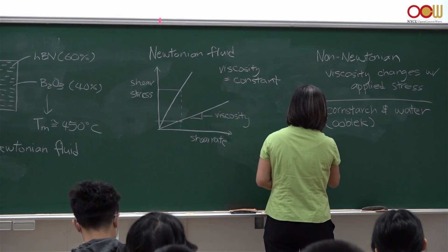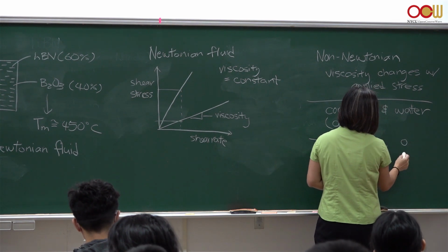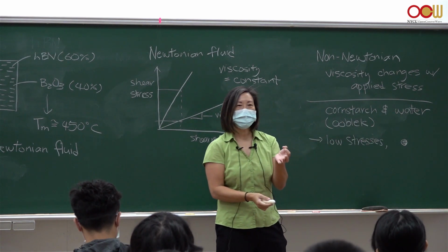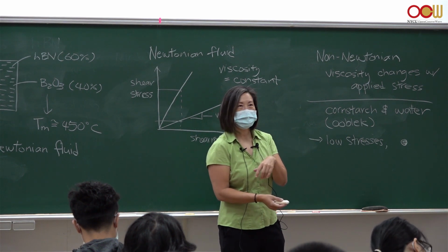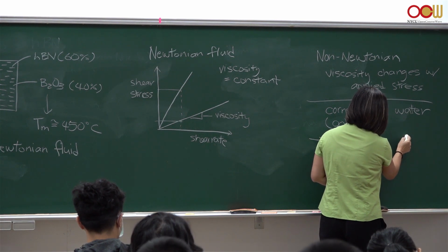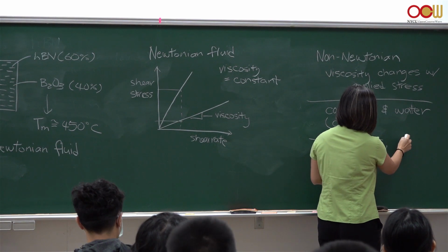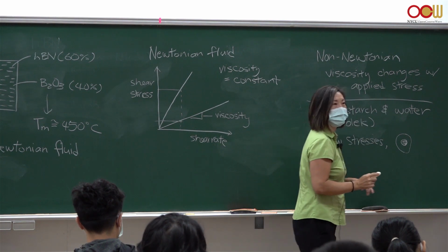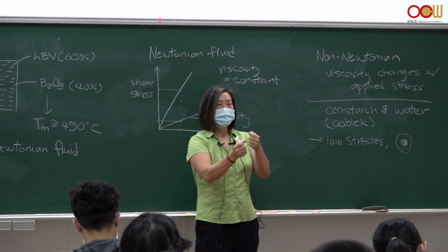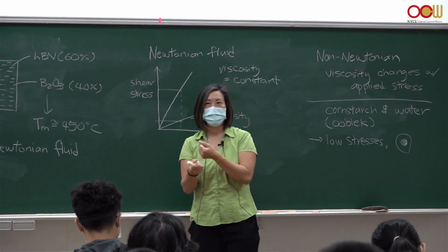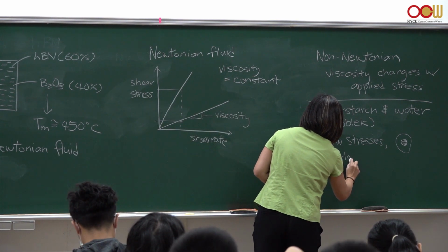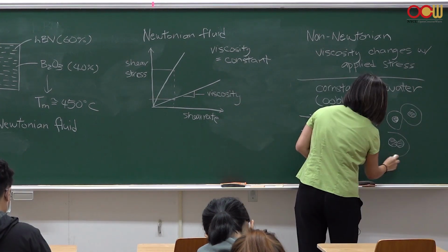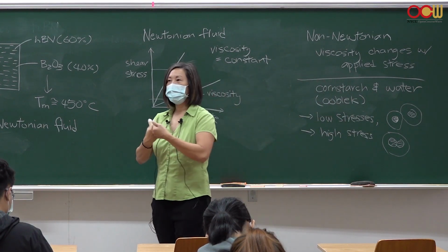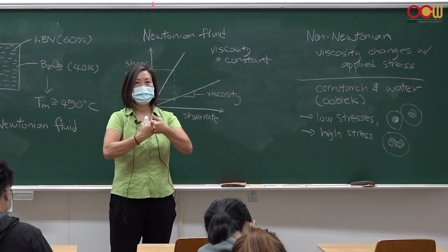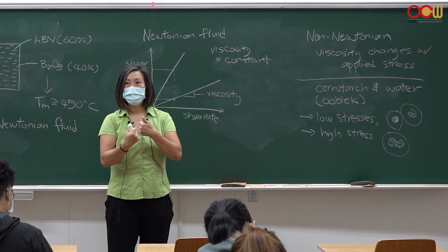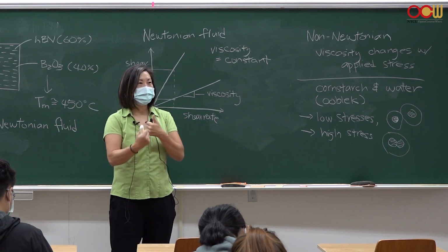So cornstarch and water at low stresses. The cornstarch particles, this is cornstarch, they're very small. They're on the order of 1 micron, 0.001 millimeters. At low stresses, each of the cornstarch particles is surrounded by water. The water coats each of the particles, so the particles slide past each other very easily. But when you apply stress, you squeeze the water out, and the particles are in touch with each other, and they get stuck. There's friction between the particles, so they get in each other's way, and they don't move as well.